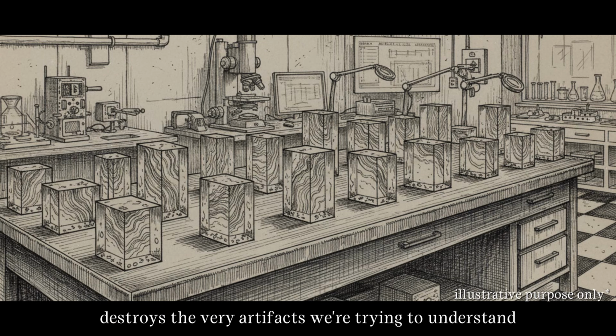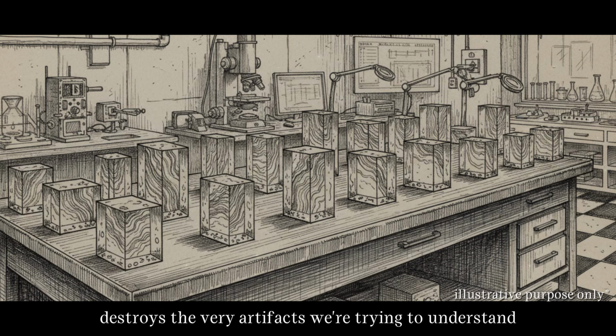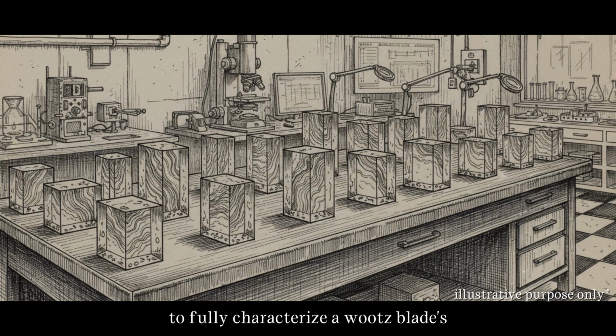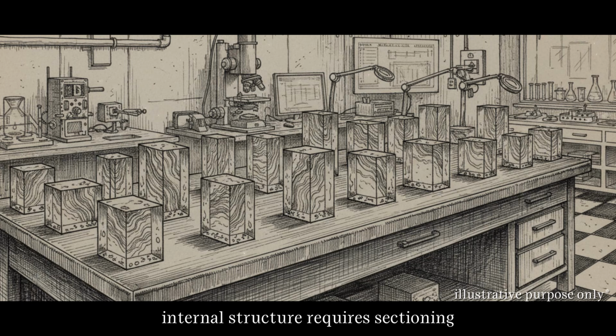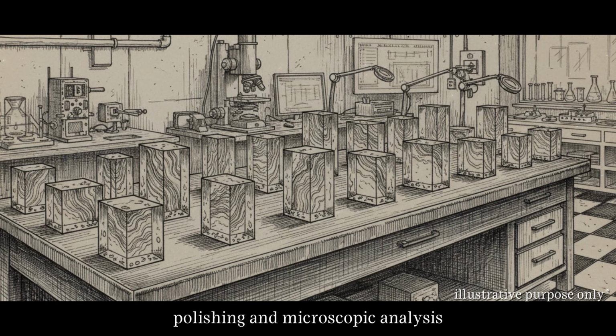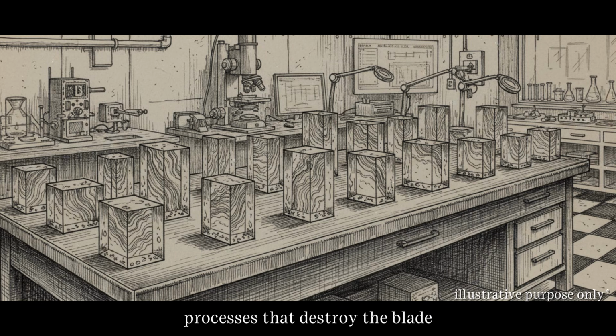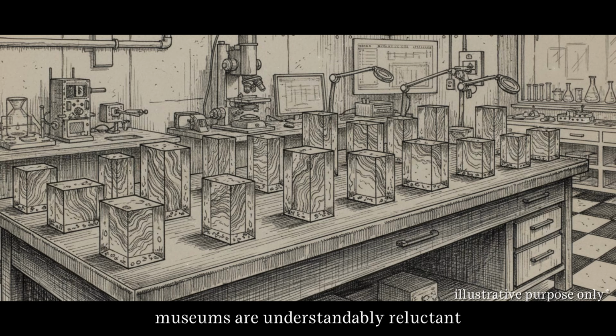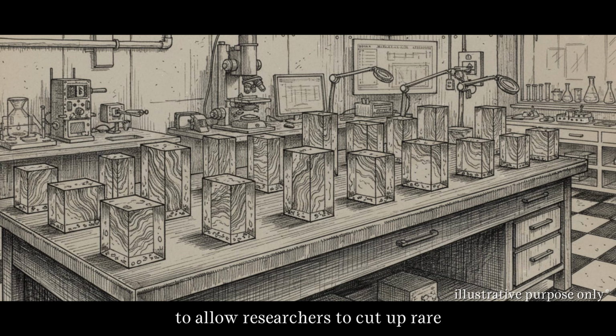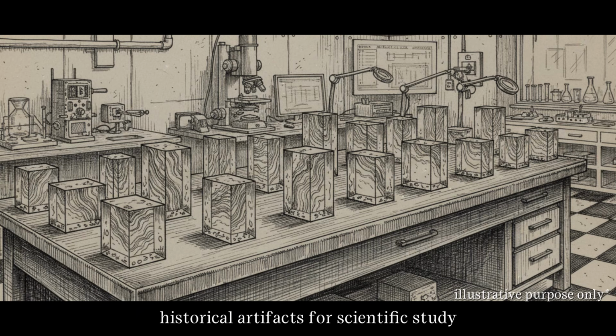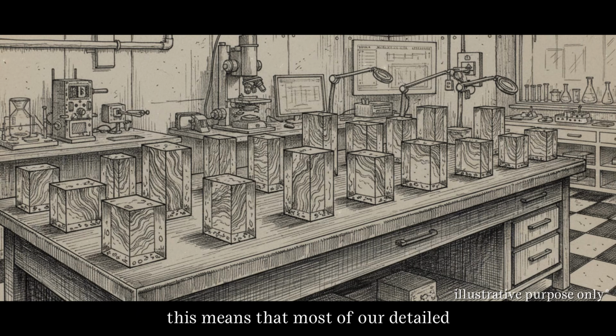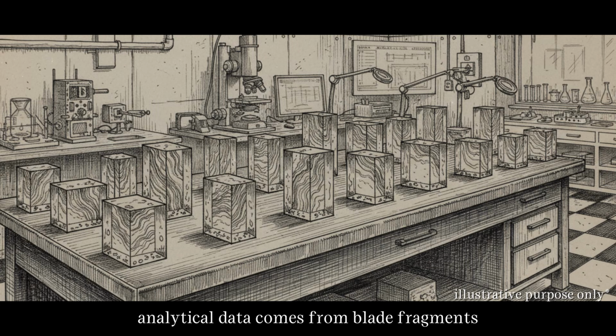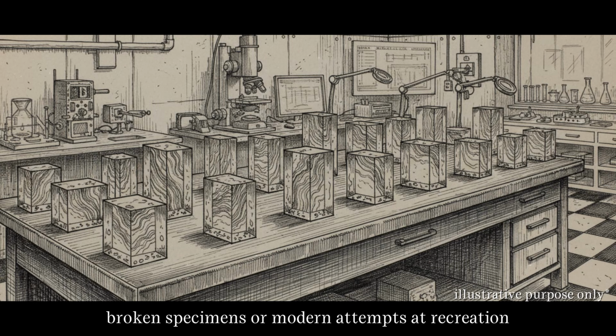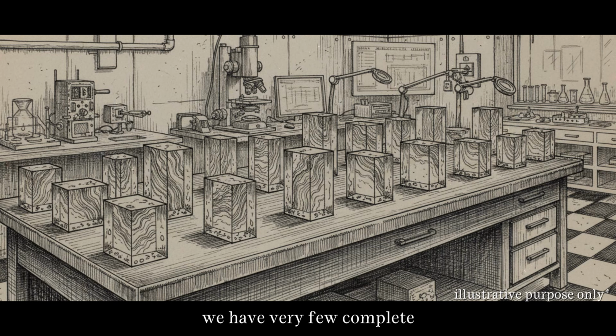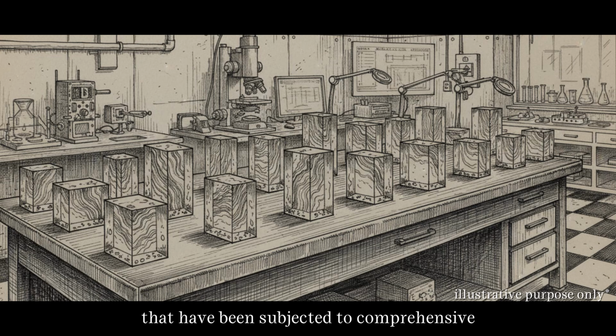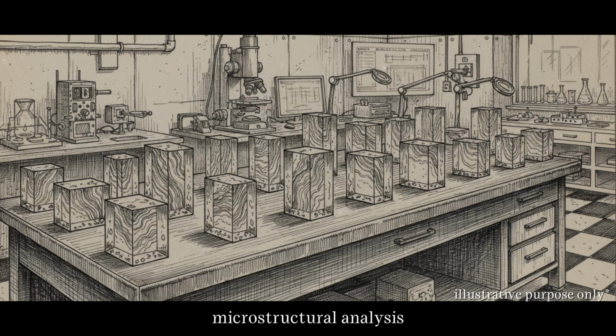Destructive testing destroys the very artifacts we're trying to understand. To fully characterize a wootz blade's internal structure requires sectioning, polishing, and microscopic analysis, processes that destroy the blade as a functional object. Museums are understandably reluctant to allow researchers to cut up rare historical artifacts for scientific study. This means that most of our detailed analytical data comes from blade fragments, broken specimens, or modern attempts at recreation. We have very few complete, intact historical blades that have been subjected to comprehensive microstructural analysis.